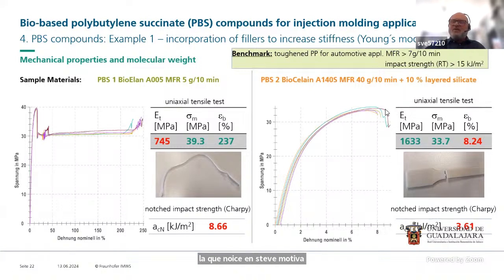We are going down. We have now tensile elongation at break that is only at 8%, which is not acceptable for the application that we need. For automotive applications, we need something that is really tough and of high strength and of high stiffness. So we have to do something. You can see it here. We are losing completely the value over here, and we're losing completely the impact strength here, measured as Charpy notched impact strength. These values are significantly going down. That is something we have to do better. The thing is that also the micromechanical processes change. You can see now here that we have transformed our material to a craze-like process.